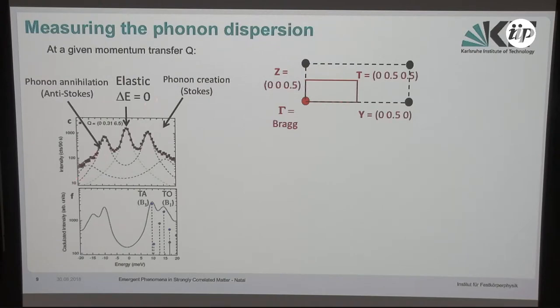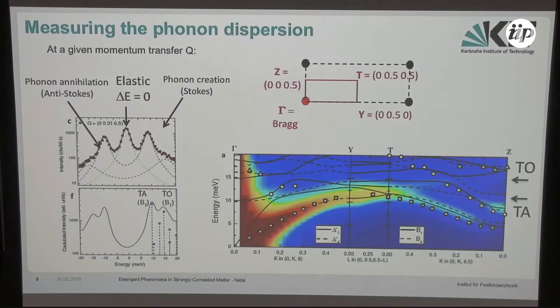To explain this a bit better, first, this is a typical phonon measurement. What you do is place yourself at a given momentum in the reciprocal space, somewhere along the path that you choose, and you scan the energy with X-rays. You can't just do a momentum scan with X-rays as easily as with neutrons. And the typical spectra are like that. You get the elastic line at zero energy loss, and then you get some phonon lines that you can compare directly with first-principles calculations and map out the dispersion of the phonons by measuring this at different Q.